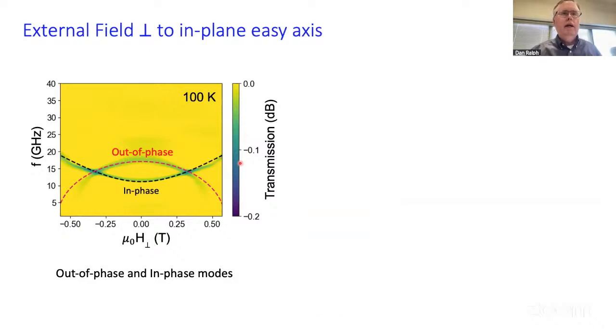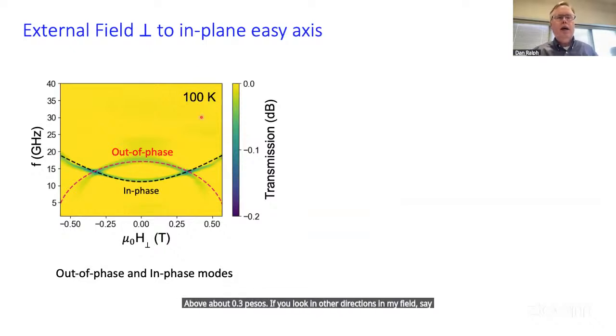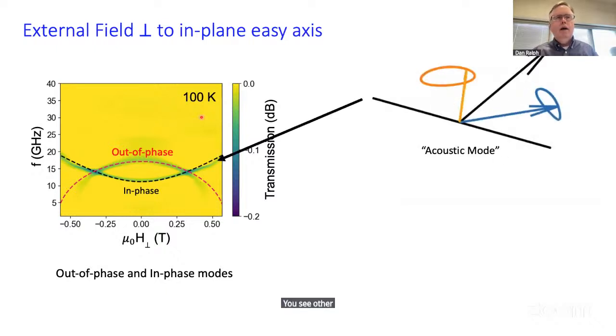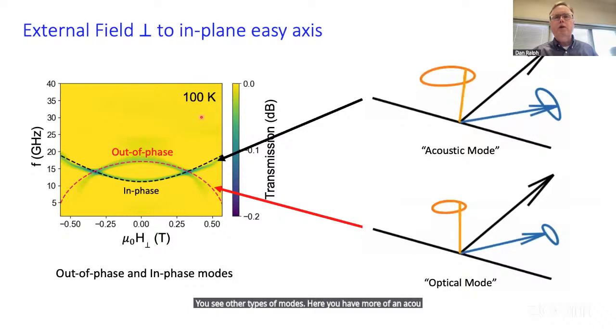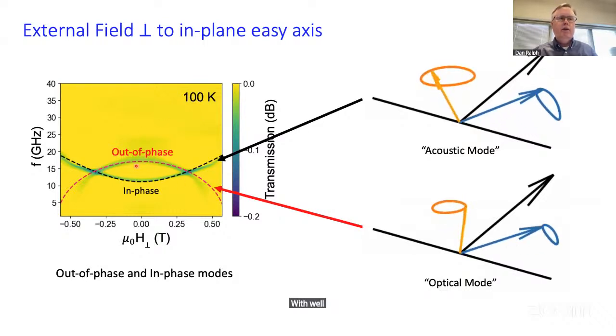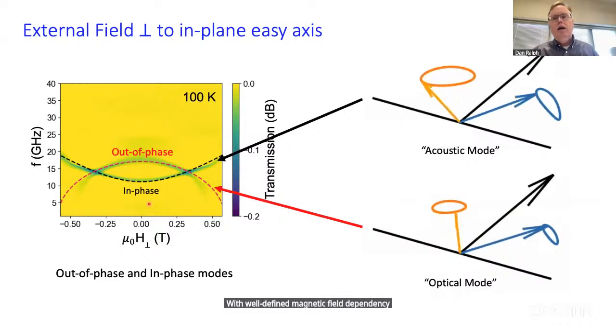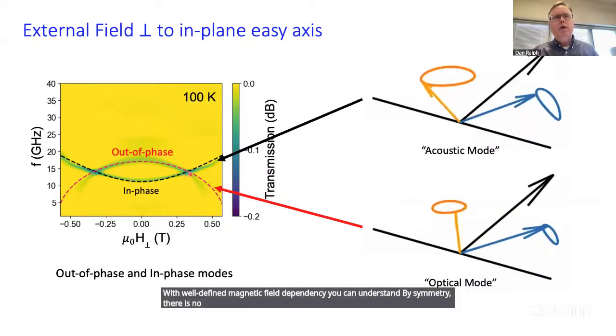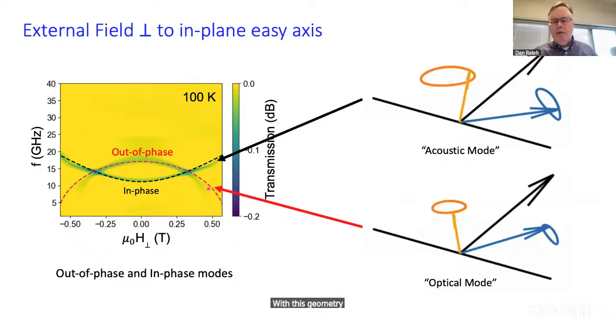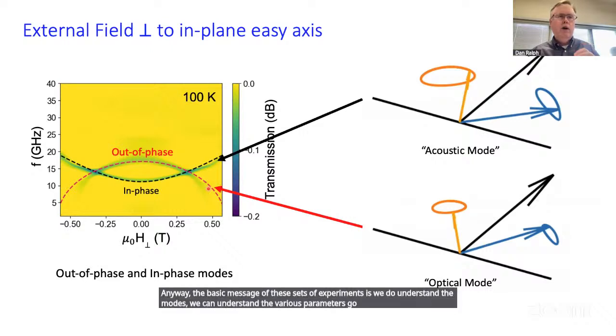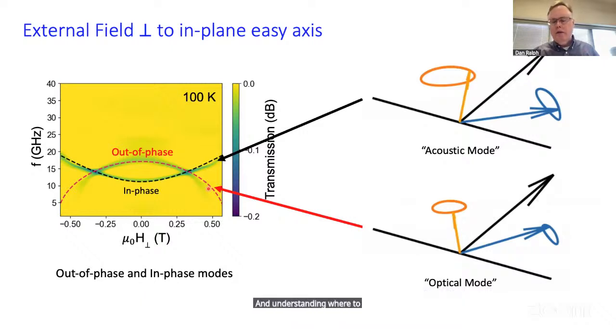If you look in other directions of the magnetic field, say here perpendicular to the easy axis, you see other types of modes. Here you have more of an acoustic mode and an optical mode with well-defined magnetic field dependence that you can understand. By symmetry, there is no coupling between these modes if you have the magnetic field perpendicular to the easy axis, and so there's no avoided crossing within this geometry. But if you have other magnetic fields, there is coupling, and you can start to see avoided crossings. Anyway, the basic message of these experiments is that we do understand the modes. We can understand the various parameters governing them, the anisotropy parameters and the exchange parameters, and understand where to look for the modes as we make smaller scale devices.